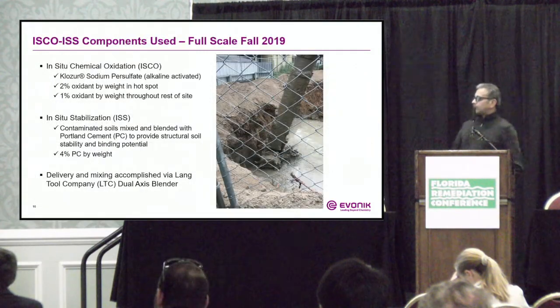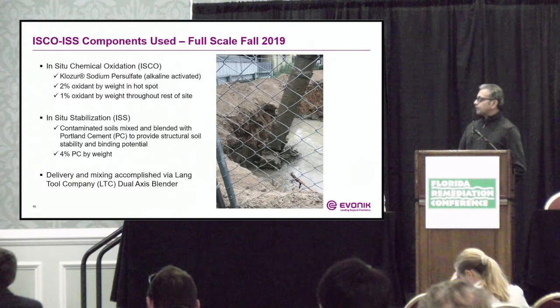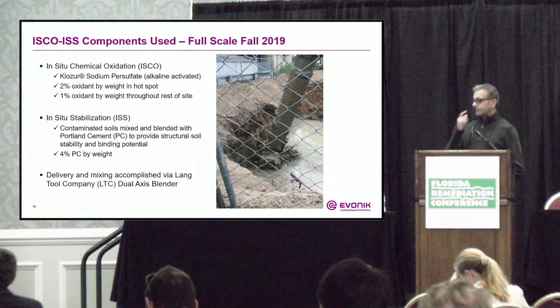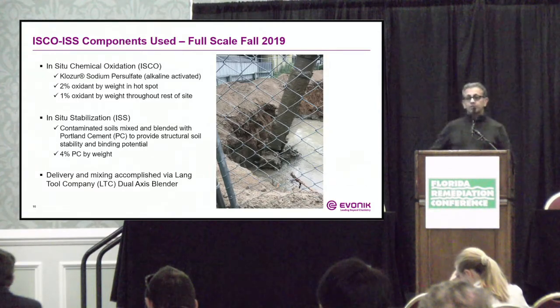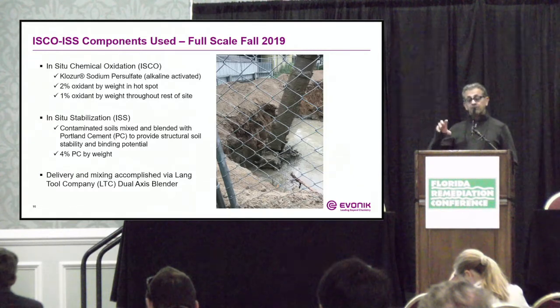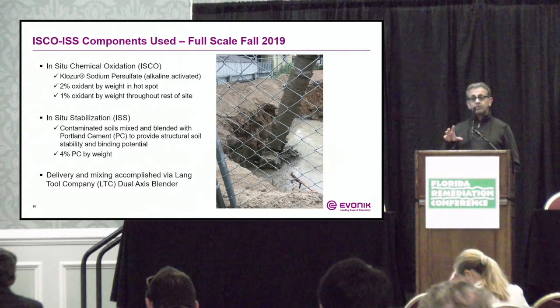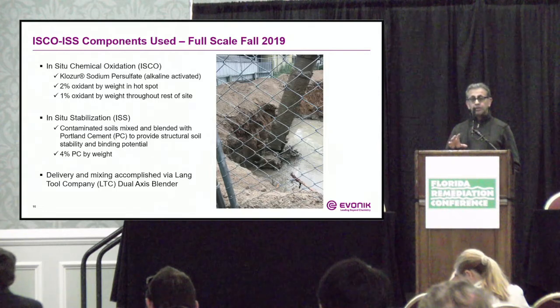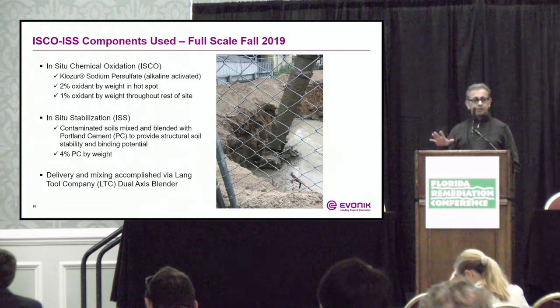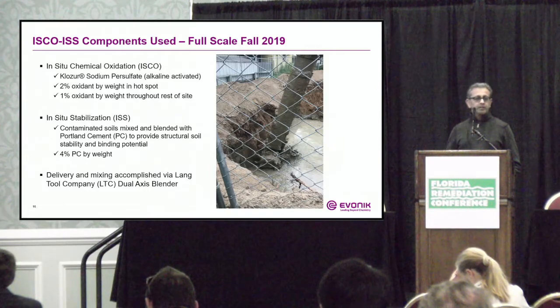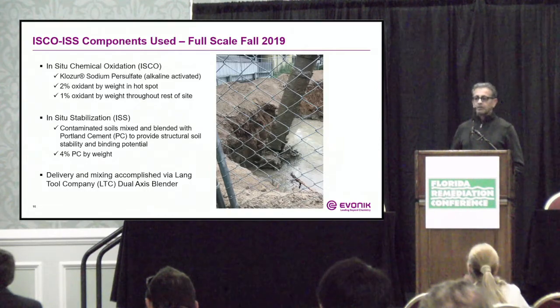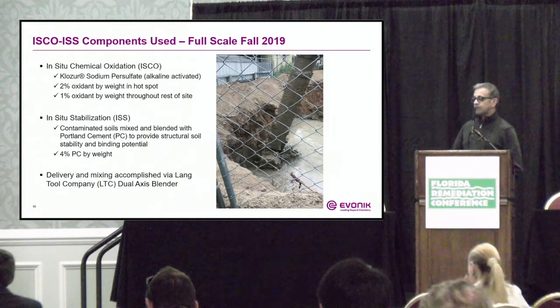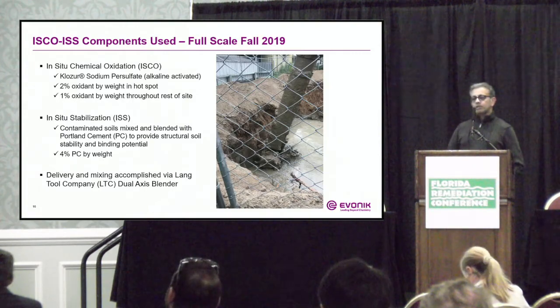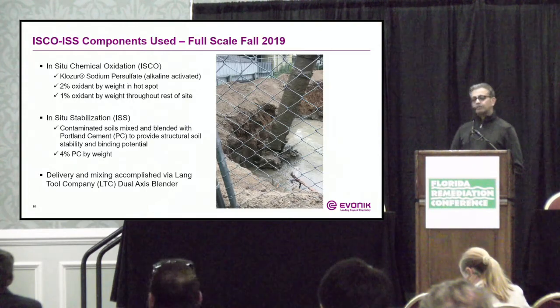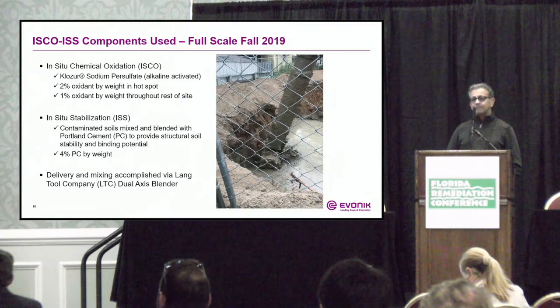For the full-scale application, which happened in fall of 2019, 2% sodium persulfate was used in the hotspot area, with very high concentrations, and 1% sodium persulfate by weight was used in the remainder of the area. Then 4% Portland cement was used throughout the entire area. So this was the mix that was implemented with the soil mixing. The delivery was done using Lang Tool Company's dual axis blender.